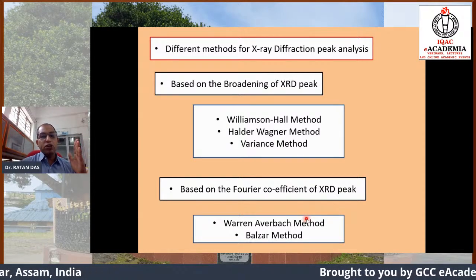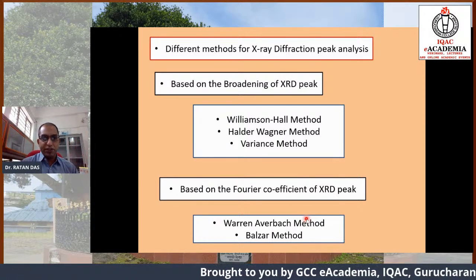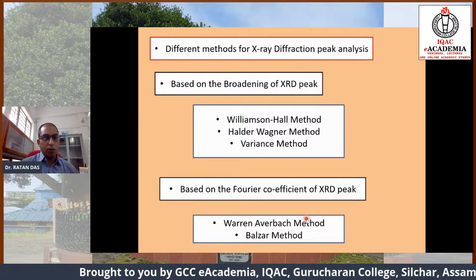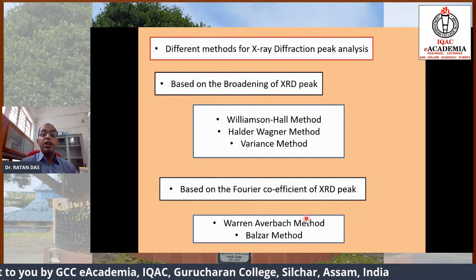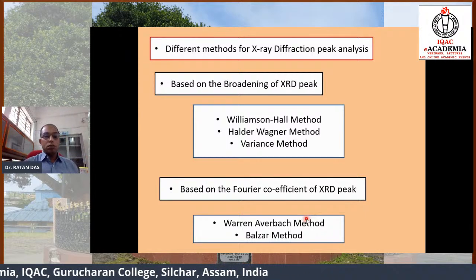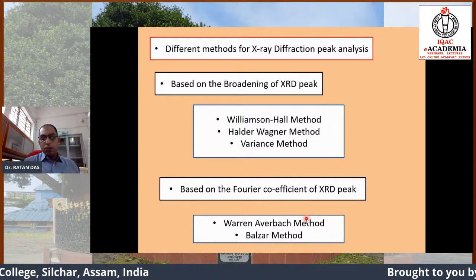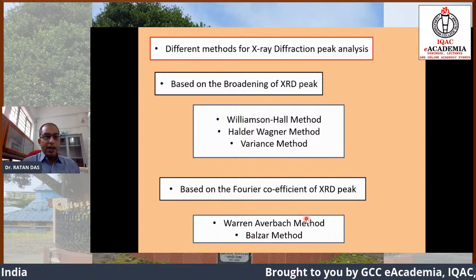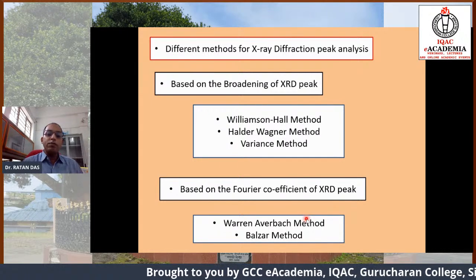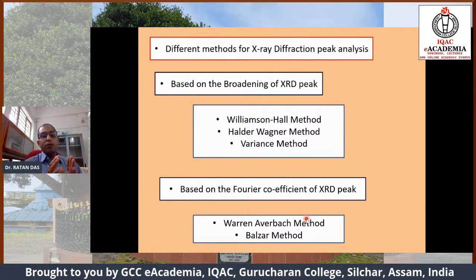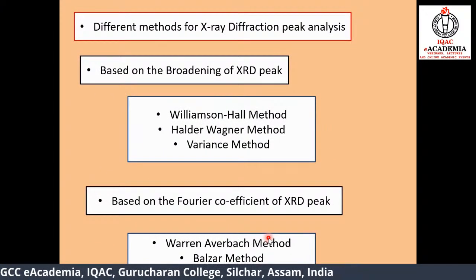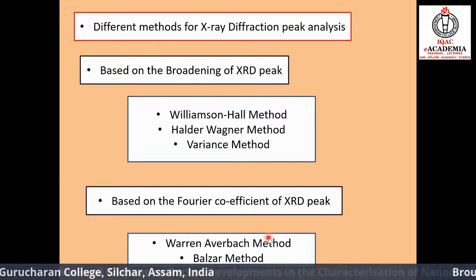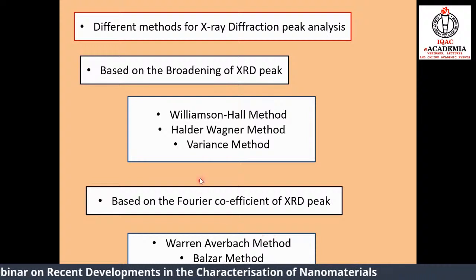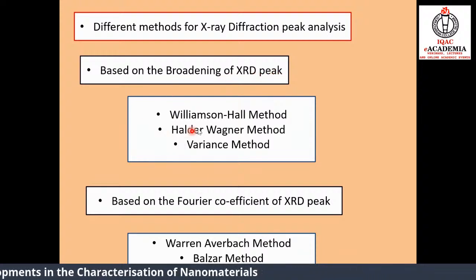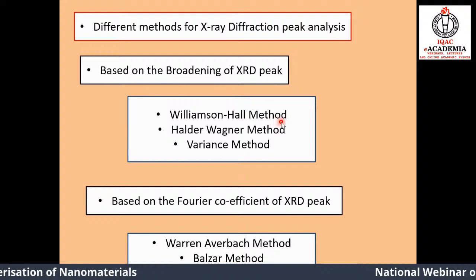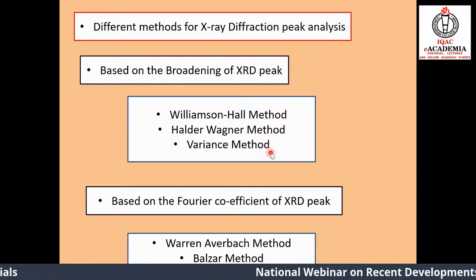So this peak analysis of X-ray diffraction pattern will provide many information. Now, based on the broadening of the X-ray diffraction peak, already I have told you, but still many things I want to add here. From the broadening we can obtain the strain, we can obtain the size, and the other information also. So based on the broadening of the XRD peak, there are methods of Williamson-Hall type, Halder-Wagner method, and variance method.